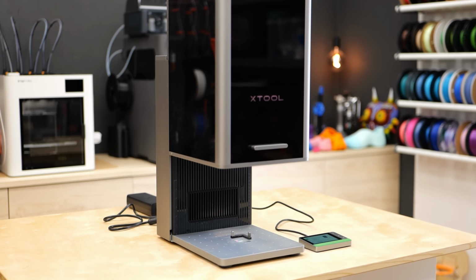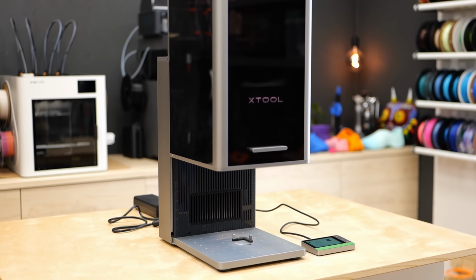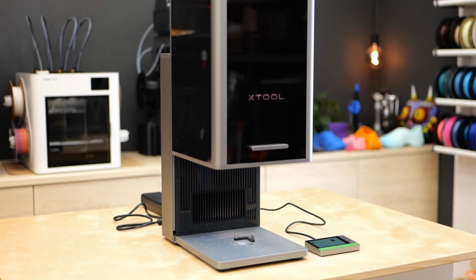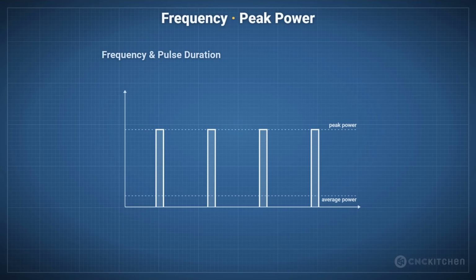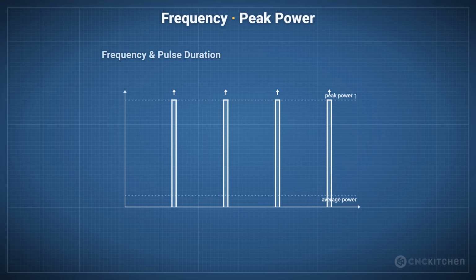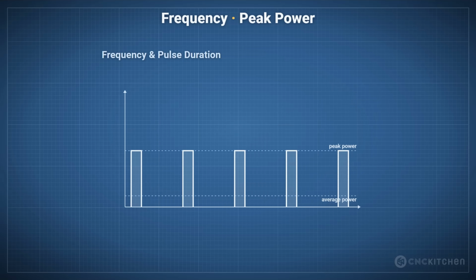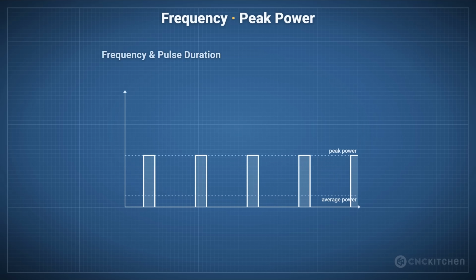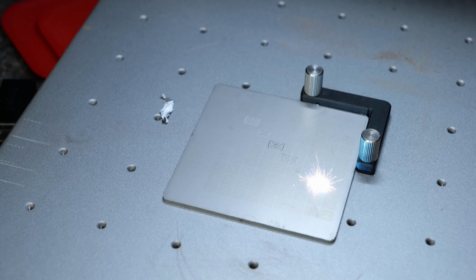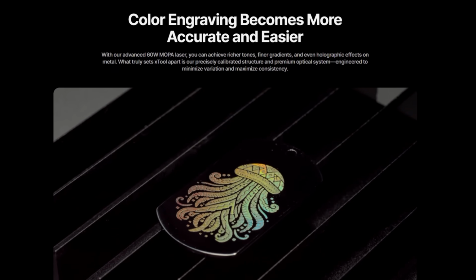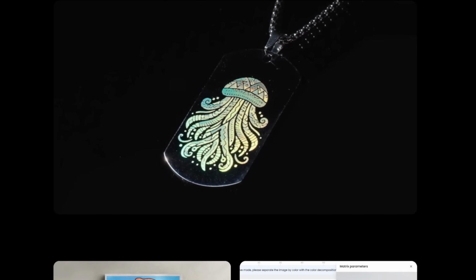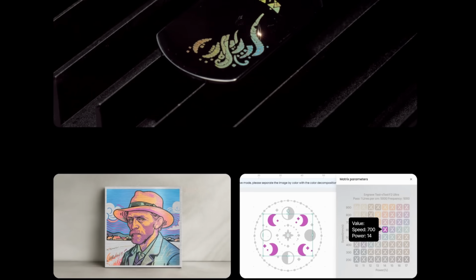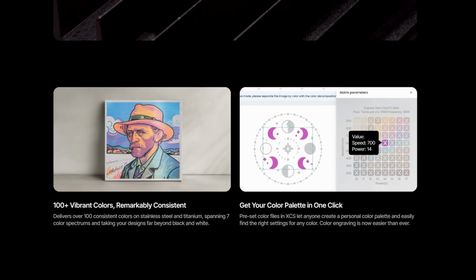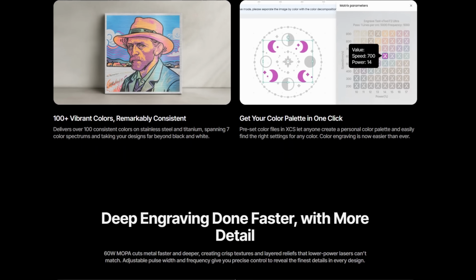And this also brings us to the MOPA laser. A MOPA laser is usually still a 1,064 nanometer fiber laser, but compared to a simple Q-switched fiber laser, it gives you much more precise control over the pulse parameters, especially pulse duration and frequency. That means you can tune even better how much energy is dumped into your surface in a given time, and therefore tune how much it is heated. This extra control is what makes MOPA lasers especially useful for things like color markings on stainless steel, where you can tune the oxide layer on the surface and therefore the color that you can see.